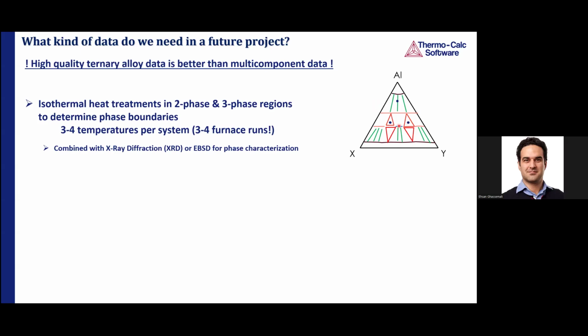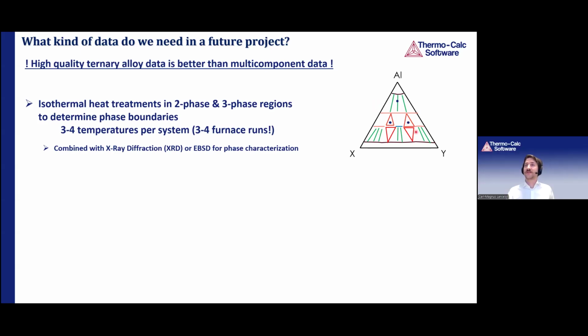And we also have a ternary intermetallic compound here, and we have some two-phase regions with the green tie lines, and also these red triangles are three-phase triangles. So if we can prepare sample chemistries to pinpoint them into these two-phase or three-phase regions, we can gather a lot of ternary phase diagram data in a single furnace heat treatment. And we can also put samples for different alloy systems in the same furnace. And if we do this for 3 or 4 temperatures, then we have gathered a wealth of data that we can use to assess these ternary systems.